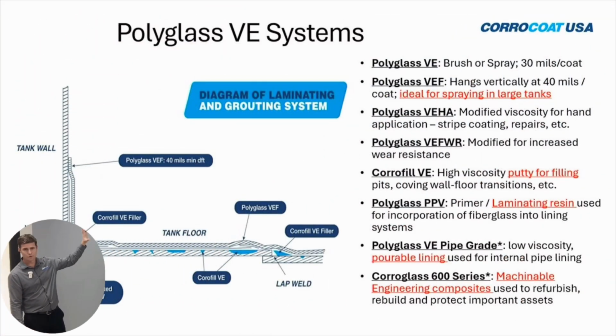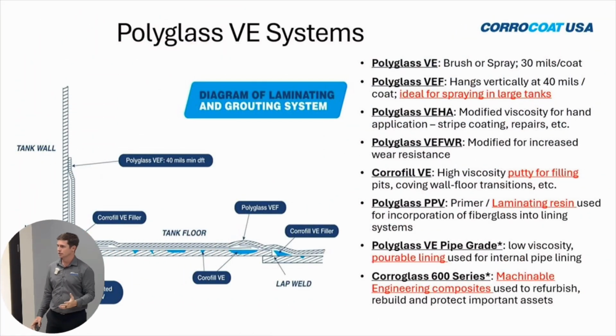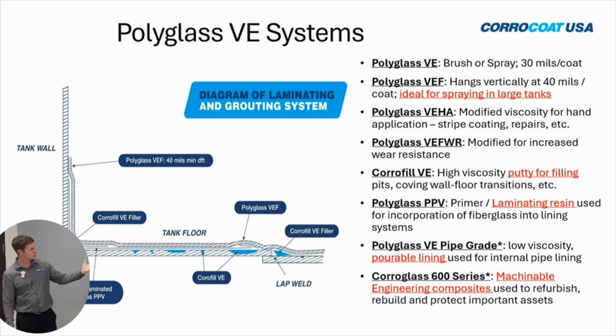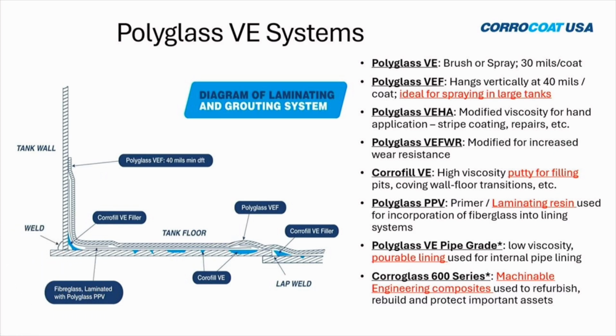I'm not going to go through every one, but pretty much every one of our coatings, we can make a system like this. So this is a cross-section of a tank floor. This will be all the same resin system. We have a laminate where we can use fiberglass laminate here at the tank floor-to-wall interface. It's a standard spec to increase flexibility and endurance. You have the filler material. We're filling in the pits. We're also filling the cove base like you just saw. And then you have top coats.